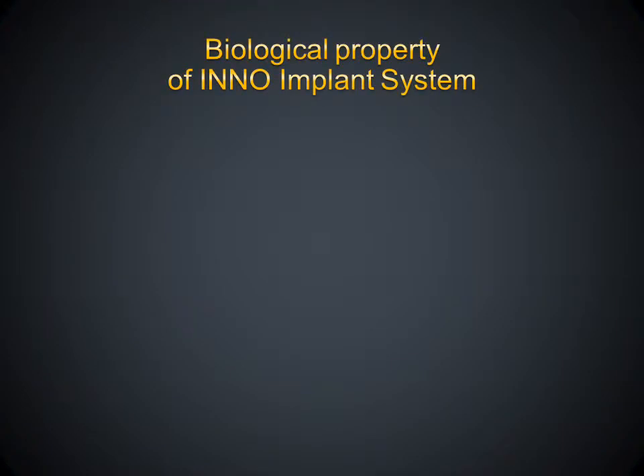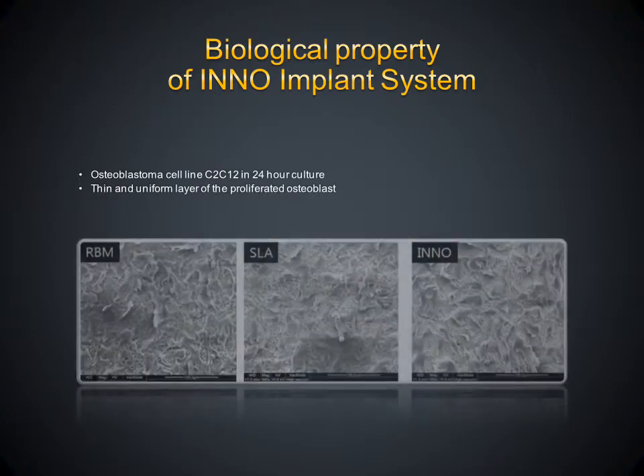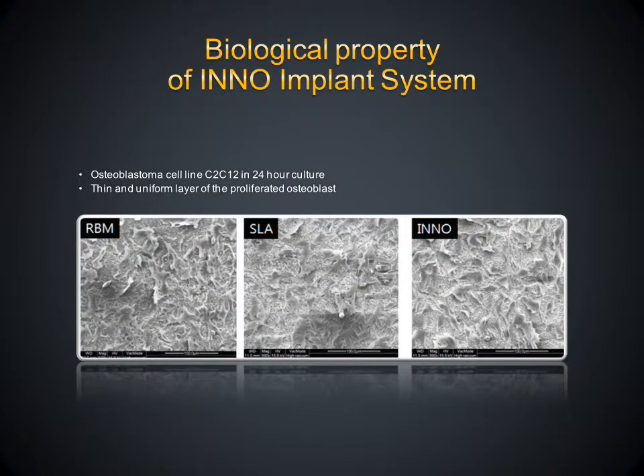Biological evaluation was done on each surface of the 3 surface modification steps: RBM sandblasting, hyperthermal acid etching, and alkali cleansing procedure. In osteoblast cell line C2C12's 24-hour culture, all steps of INNO implant show aggressive growth of cells on implant surfaces. The procedure of INNO implant surface modification is safe in biological response.